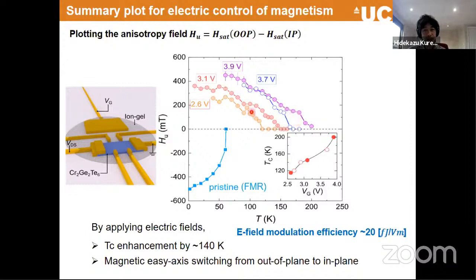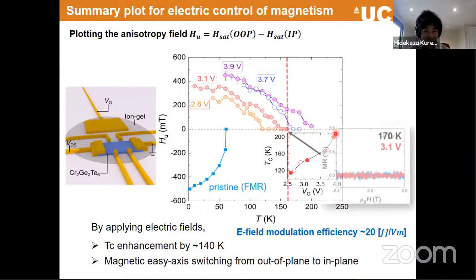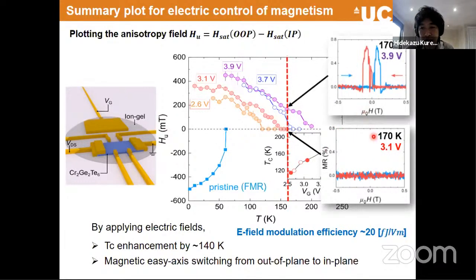Now, it's very different compared to the bulk materials or undoped materials characterized by FMR experiments, where first of all the sign of this is different, meaning that there is a switching of the magnetic moment anisotropy, and also, as I already told you, there's a significant enhancement of the Curie temperature. Okay, and this is a quick demonstration. You can turn it on and off by applying the electric field, and you can see that we can kill it completely by increasing the electric voltage, so we switch the magnetism on and off by just an electric field.